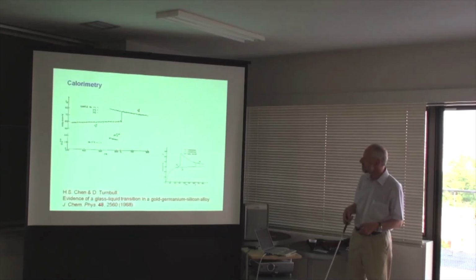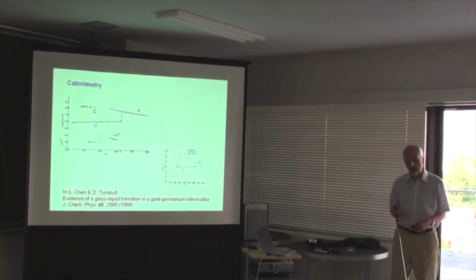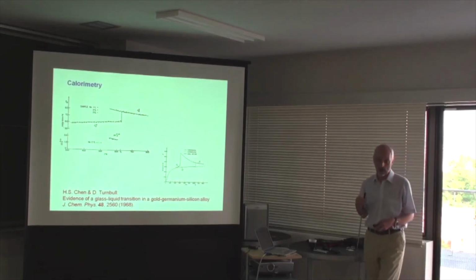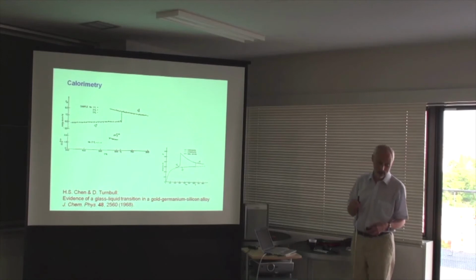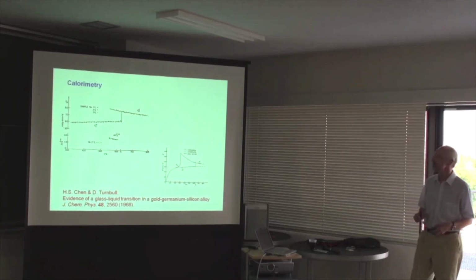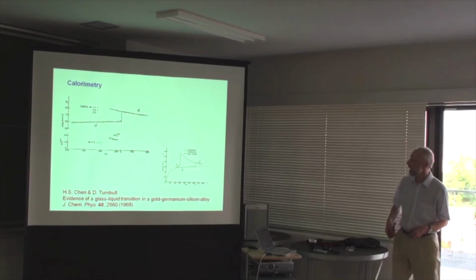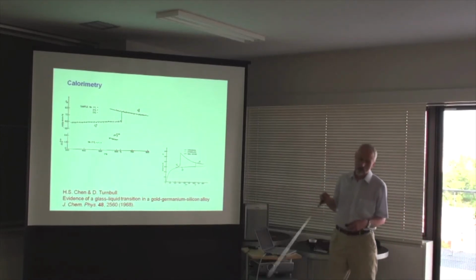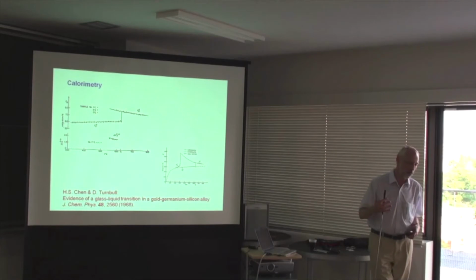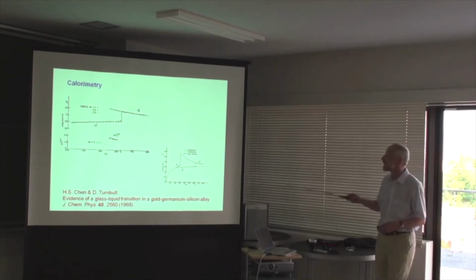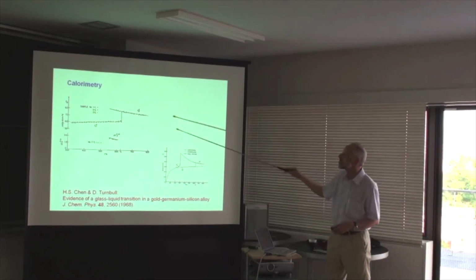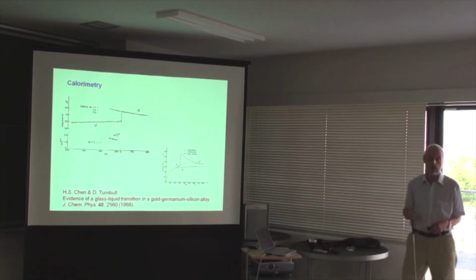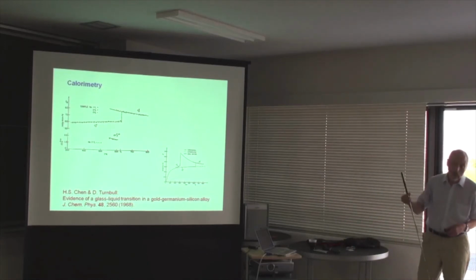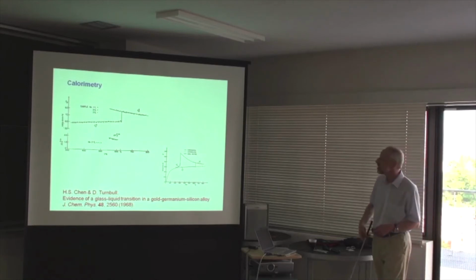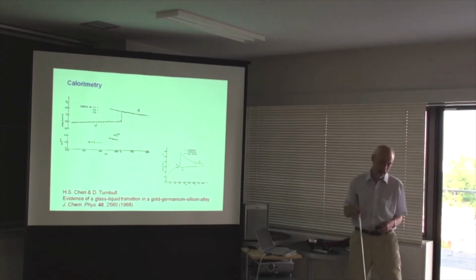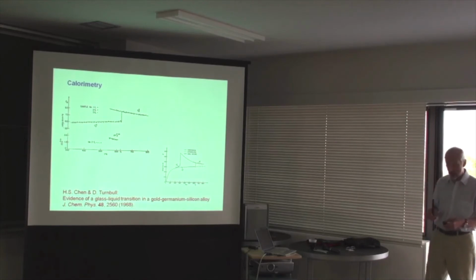That's 1960. For a long time, people were reluctant to accept that metals really could make glasses. They did not want to believe that you could get a metallic glass. And David Turnbull at Harvard was very instrumental in showing that these materials showed the same sorts of phenomena, in particular, in this case, a calorimetric glass transition, a change of specific heat at the glass transition, that would mimic what you get in traditional glass systems. So people began to think that maybe these could be glasses really.